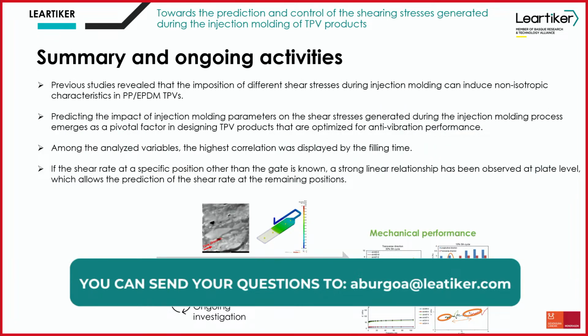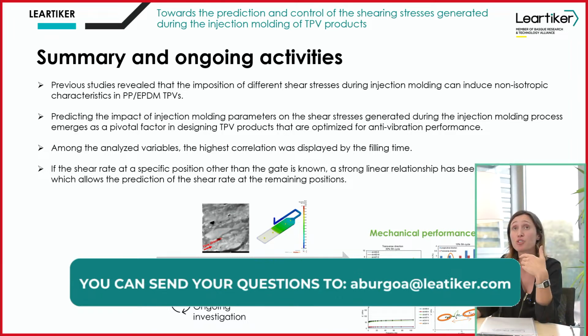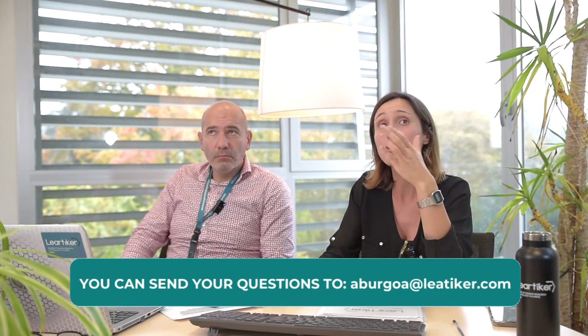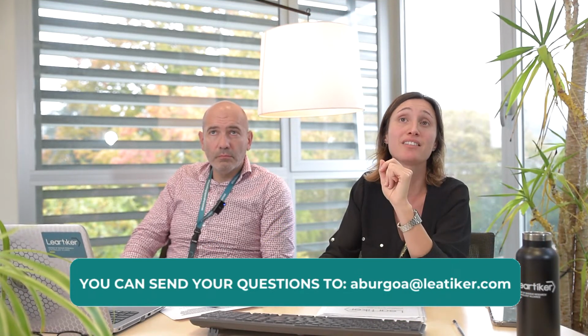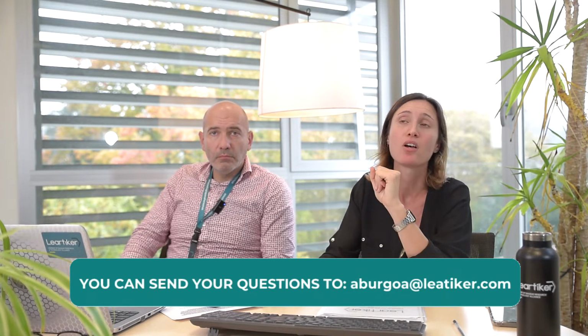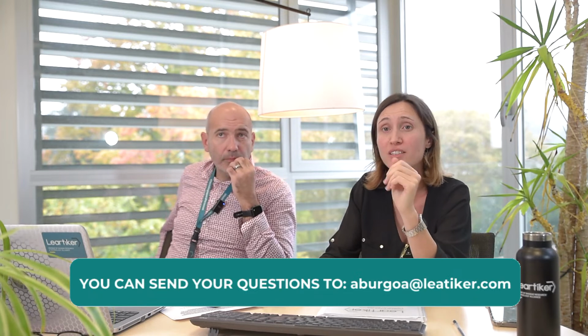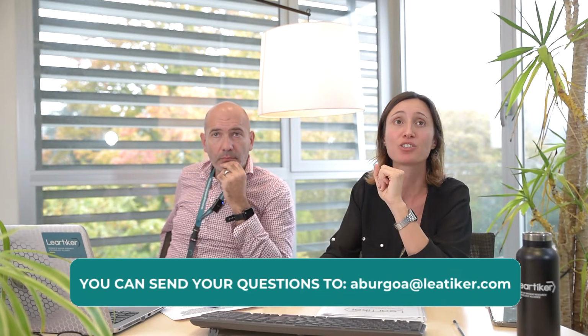So as a summary, we can see that previous studies that we have done have revealed that the imposition of different shear rates or shear stresses during the injection molding can induce non-isotropic characteristics in PP-EPDM TPVs. So that's why predicting the impact of these injection molding parameters on the shear stresses generated during injection molding emerged as a pivotal factor in designing TPV products that are optimized for anti-vibration performance and for the new requirements that are appearing in the electric vehicles.